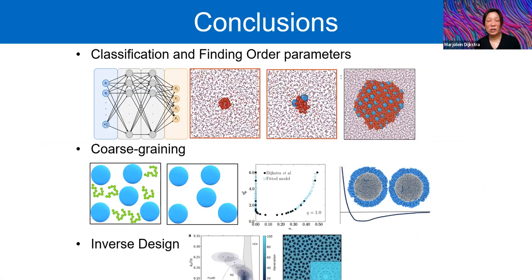So we use machine learning to classify different phases, to find good order parameters, but also to detect local structures and influences in nucleation simulations. We can also use machine learning to coarse-grain systems. I've illustrated that with a simple colloid-polymer mixture, but we can also machine learn the forces, for instance, in the case of ligand-stabilized nanoparticles. And finally, we also developed inverse design techniques where we can really inverse design liquid crystals, crystals, but also quasicrystals.